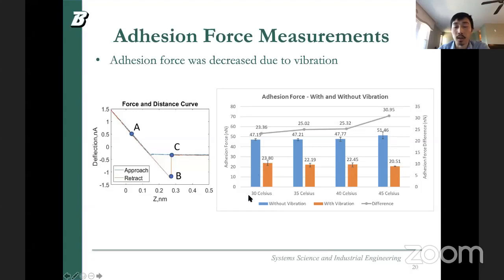We did experiments comparing different temperatures and the adhesion force without vibration and with vibration. This is without any vibration, and this is with vibration. We can clearly see that without vibration, the adhesion force increases a little bit from 30 degrees C to 45 degrees C, but if we apply the vibration, the adhesion force stays consistent or even gets a little lower. There is an adhesion force difference between with and without vibration. This trend shows that at a higher surface temperature, applying vibration gives a larger gap in adhesion force.